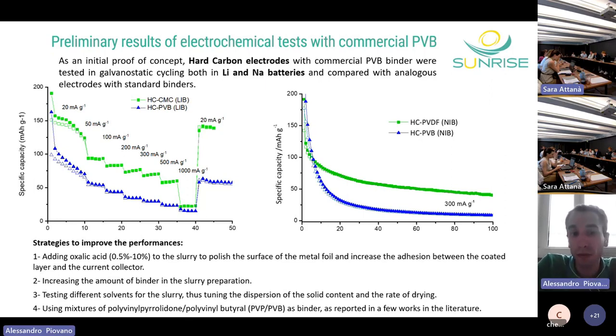To increase the amount of the binder in the slurry preparation, to test different solvents in order to properly tune the dispersion of the solid content and the viscosity of the slurry. And finally, to mix the PVB with other polymers, such as polyvinylpyrrolidone, as is already reported in a few works in the literature.